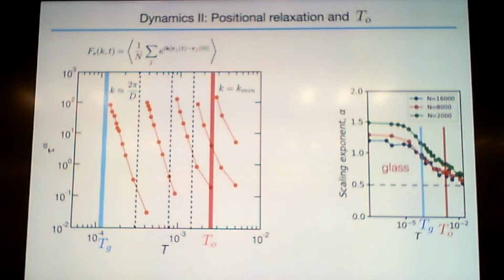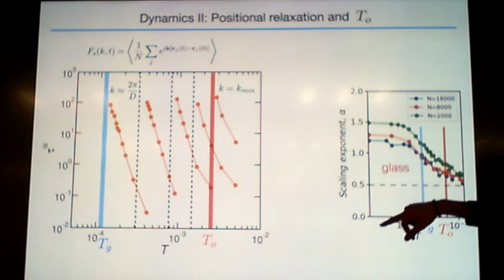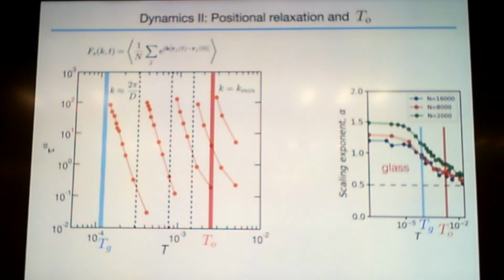And this you can do for different modes. It doesn't matter. So what happens here is basically you are crossing into a glassy region where things don't equilibrate anymore at any given finite time scale, and you are crossing from one class to another. It's a very subtle difference, right? You're crossing from class 3 to class 1. But these are different structures, measured by the fluctuations at large length scales, these are different phenomena. Yes, it is very subtle, and people might say, fine, your exponent jumps from one to another, but still, these are different phenomena.